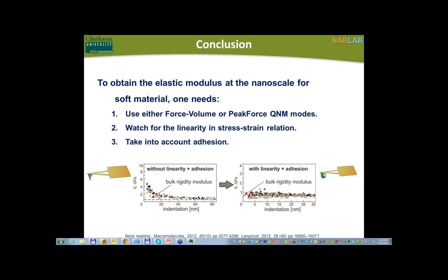What about biological cells? Everything presented is okay for polymers. For really very soft materials, even long-range force is important — when you approach your probe to the sample, you can already deform it before you reach contact. For cells, this long-range force is very much pronounced because cells are surrounded by a sort of entropic brush. Taking that into account is paramount for quantitative analysis of those, but that's a further development of what is presented here. We'll probably do another webinar for that in the future.